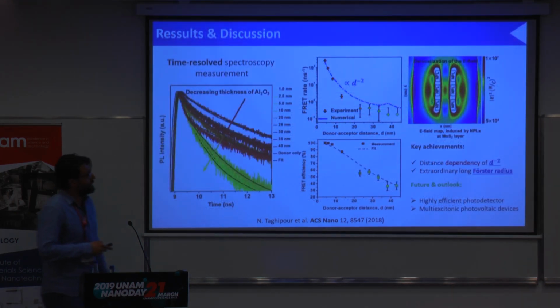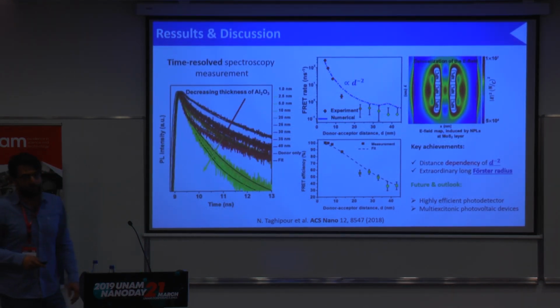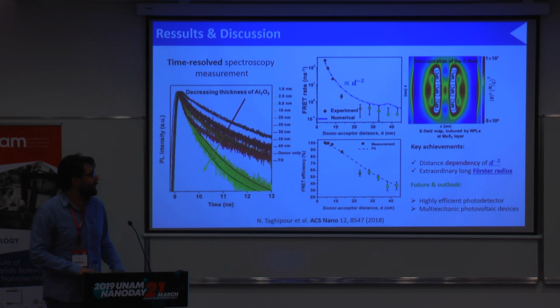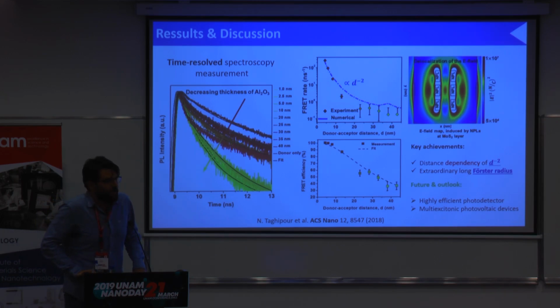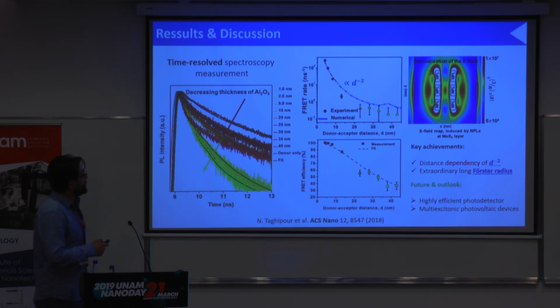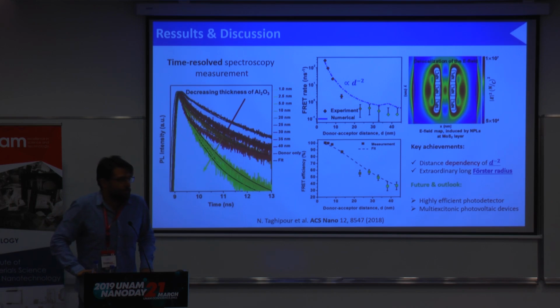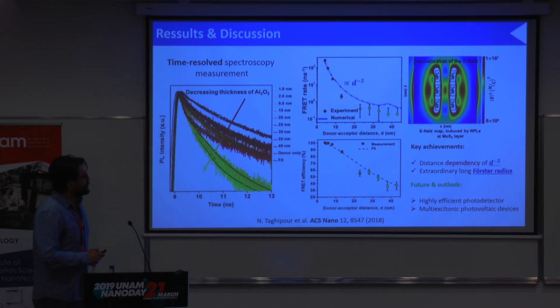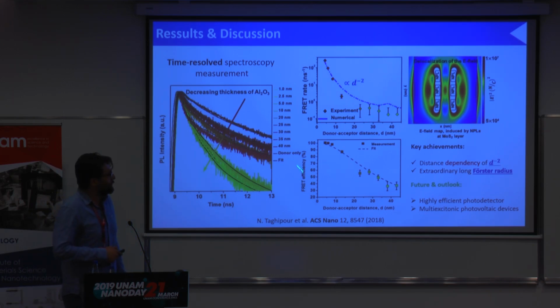After fabricating the devices, using time-resolved fluorescence spectroscopy, we looked at the fluorescence decay curves of our samples. You see that by decreasing the dielectric spacer thickness, the fluorescence decay curve is accelerated. It shows that we have energy transfer from our donor to the acceptor. So by using these data, we calculated the rate of the energy transfer and also the efficiency.